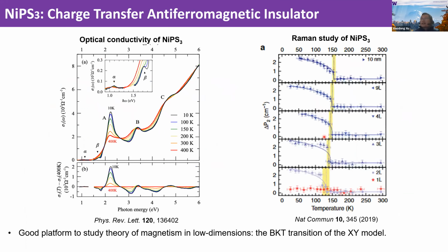There are also optical studies done on nickel phosphotrisulfide. In this particular work, they studied the optical conductivity as a function of temperature, and they observed three resonance peaks called A, B, C. A, B, C are generally attributed to charge transfer excitons. What's interesting in this work is they observed the exciton oscillator strength transfer as the temperature goes below the Néel temperature. From here, the paper basically concluded there's a strong coupling between the electronic degrees of freedom and also the spin degrees of freedom.